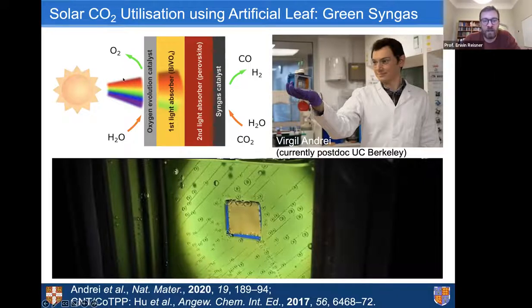And you can see, I will show more chemistry, of course, in a second, but just to keep it simple as a start, we have two light absorbers here. One light absorber is a wide band gap bismuth vanadate light absorber that's coupled to an oxygen evolution catalyst. And the second light absorber is a lead halide perovskite, to be specific a more advanced triple cation lead halide perovskite that's particularly suitable here. And this perovskite then can drive a syngas catalyst.